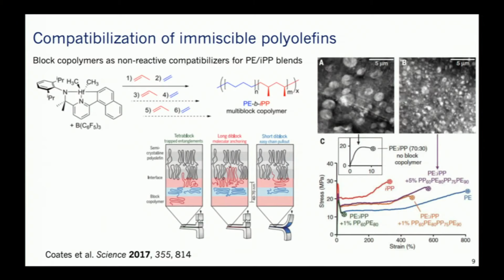So one option is to try to turn them into new polymers. And that is very challenging because many of these polymers in the waste streams are mixtures. And that means the properties of the mixtures are not the same as the properties of the pure polymers. One approach, which comes from the Coates group at Cornell and has been widely imitated, is the design of compatibilizers, which can reduce the incompatibility between the different phases that are created when you mix different types of polymers. Even polymers which are chemically as similar as polyethylene and polypropylene will not form homogeneous mixtures without one of these compatibilizers. And the compatibilizer in this case, designed using a clever catalytic route using both monomers, is to create a multi-block copolymer containing both polyethylene blocks and polypropylene blocks, and you have to make several of these blocks in order to reduce the interfacial repulsion between these two types of polymers.